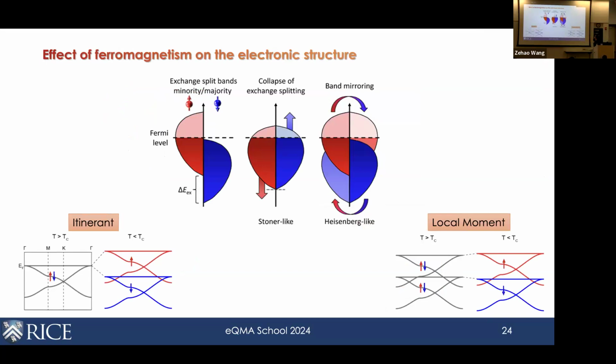So we know that there are two extreme limits of how to understand magnetism. One is the Stoner-like mechanism, where you have the band splitting into spin majority and spin minority states, and this exchange splitting should close across the ordering temperature. That's the Stoner-like behavior. On the other limit is the local moment picture, and here the local moments themselves don't disappear across the ordering temperature.